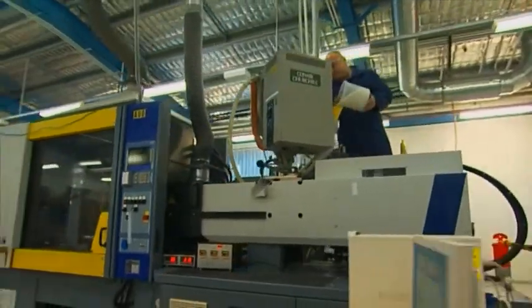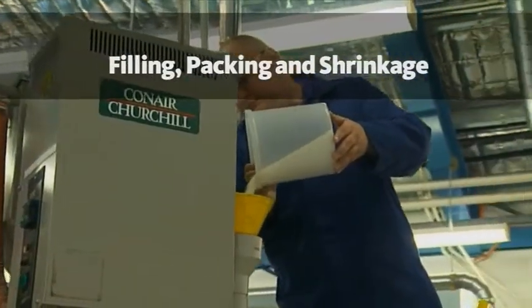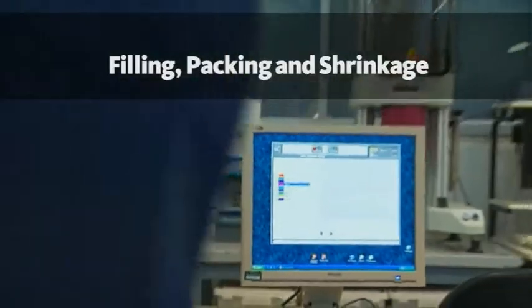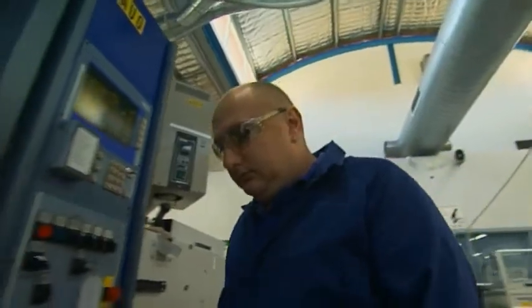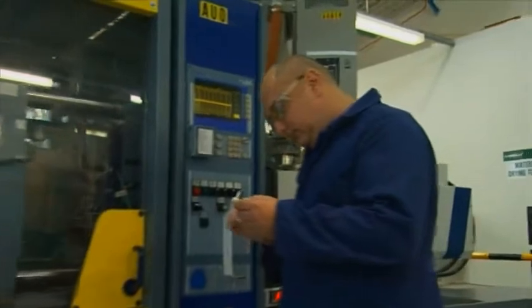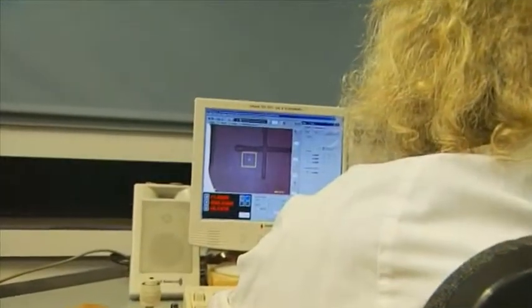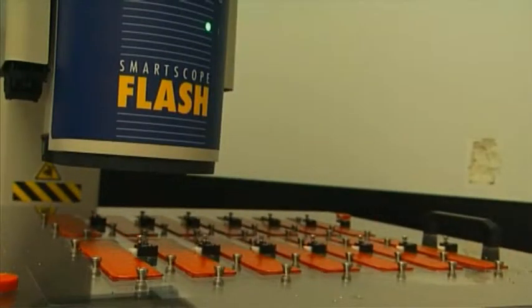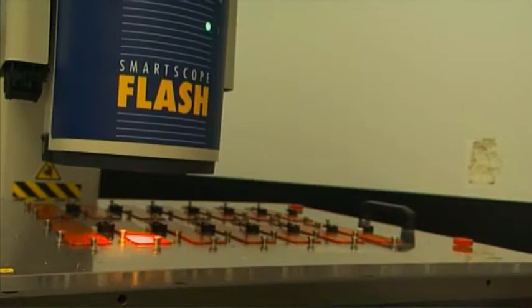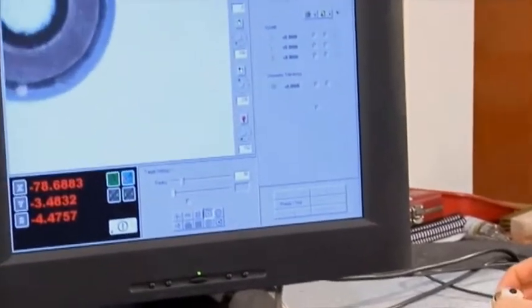The next level of testing is filling, packing and shrink. To measure the actual shrinkage behaviour of a material, 25 parts are molded. After being conditioned, the shrinkage in the direction of material flow and at right angles to the material flow is measured. When manufacturing the mold for a part, toolmakers need precise shrinkage information to ensure the finished part is dimensionally accurate. The shrinkage parameters obtained by these series of tests accommodate these requirements.